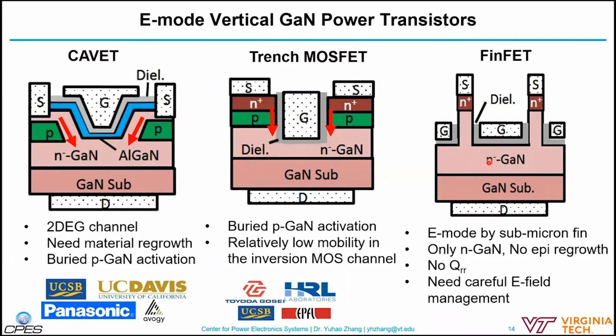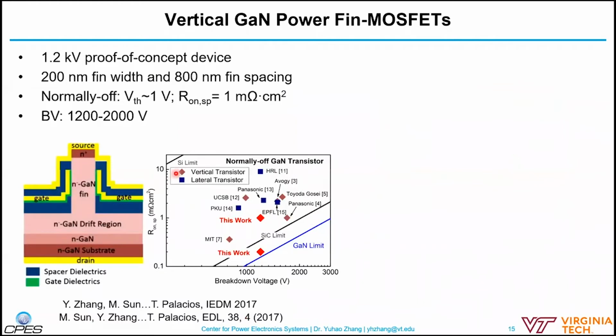And since there is no p-type, there is no reverse recovery charge, and no need for the p-type regrowth, and a lot of the material issues related to the p-type gallium nitride can be eliminated. But essentially, this structure needs very careful electric field management design. Okay, so in 2017, we demonstrated this 1.2 kV proof of concept device, and we used a fin width of about 200 nanometers, and it achieved normally off operation with breakdown voltage up to 2000 volts.